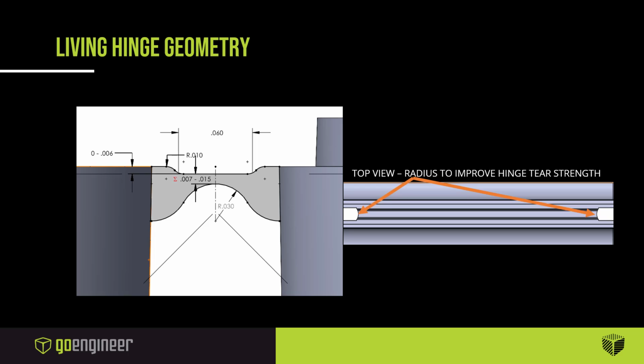So the first thing is our living hinge geometry. Our geometry proportion to the living hinge that we show here has been around for 4 decades, as I said. The hinge's thickness, radius, and length all need to follow this basic setup. So our keys are the thickness, the 7 to 15 thousandths thickness, the 30 thousandths full radius, and this flat on the top of the hinge. So within the 7 to 15 thousandths inch thickness range, a restriction to the melt flow occurs that causes the plastic molecules to orient to where they're perpendicular to the flex direction. What this does is allow those molecules to actually bend and stretch without messing up the molecules.